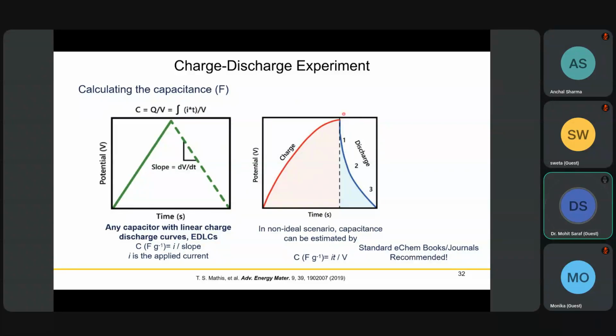But if it is not the case, if your charge and discharge curve is not linear, in these non-ideal cases, the area under the curve in the charging and discharging region will appear different. This means the Coulombic efficiency will be different, because if you divide discharge by charging area, it will differ, and the slope at different locations will be different. So at different points the slope will differ, and this equation does not apply.